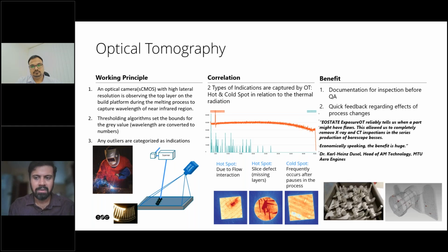There is one customer of ours, MTU. What they do is they first calibrate the optical tomography, so that if they see any process defects, the process defects are for additive manufacturing, right? It's not just with us, it is there with every other OEM within this technology. So they say you need not have the part checked for its quality by radiography or so, but much before that, you will know these are all the places where you can expect defects. So if your defect percentage is beyond a certain limit, reject the part directly.